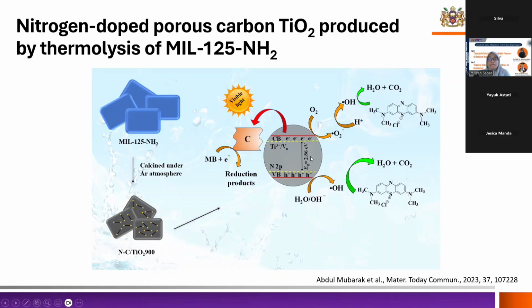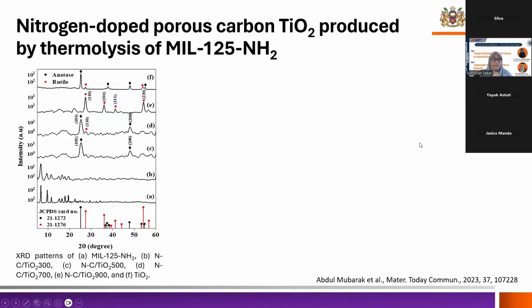So it has shifted the activity of the photocatalyst into the visible light region, and this carbon increased the absorption of the photocatalyst, and also it acts as a charge carrier for the electron, the negative electron, and further enhances the reduction of methylene blue dye. So this is the XRD spectra of the aminated MIL-125 from the first.